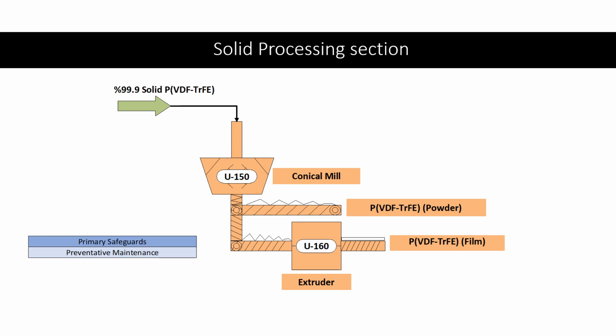The conical mill will have a wide selection of screen sizes and rotor configurations, which will enable us to achieve the desired particle size distribution. The time to mill the 51-pound batch of dried copolymer will be approximately 15 minutes. 90% of this milled powder product will be sent via powder bins on a conveyor belt to be stored as a final product, where 10% of the milled powder will be conveyed to a film extruder.